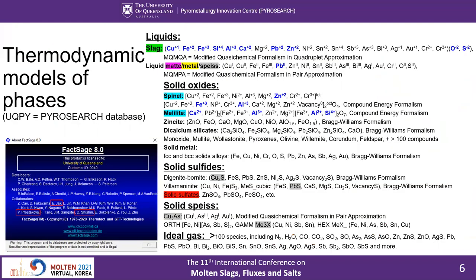The review of reactions gives an idea about the phases that need to be modeled in order to describe the process. The most important phases are liquid slag, matte, metal, and speiss. The slag is modeled in a separate solution from the other three and is assumed to be an ionic liquid, meaning that metal cations always have anions as first neighbors. When sulfur dissolves in slag, it is also assumed to be in ionic form. Oxygen and sulfur compete for positions next to cations and have preferences. The model does not allow deviation from the stoichiometry determined by charge. What the model does allow is the description of second-nearest-neighbor short-range ordering between acidic silica cations and basic cations such as calcium or zinc, which has a major impact on the entropy of mixing.